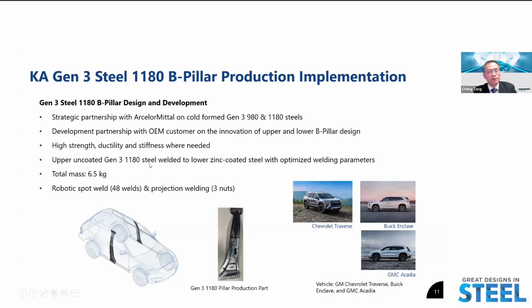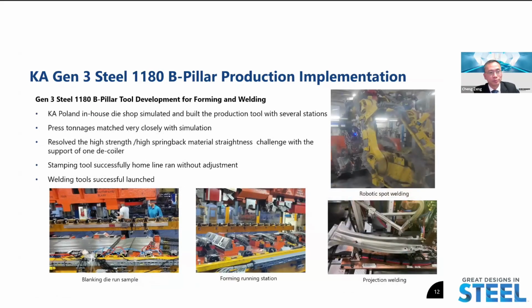So high strength, ductility and stiffness were designed into the parts where needed, and the upper uncoated Gen 3 steel 1180 welds to the lower coated steel with our optimized welding parameters to avoid any corrosion concern. It also maintains the crush performance as needed. Total mass is 6.5 kilos. And then the robotic spot welding has 48 spot welds, projection welding of 2 nuts on the Gen 3, and a few others on the other material.